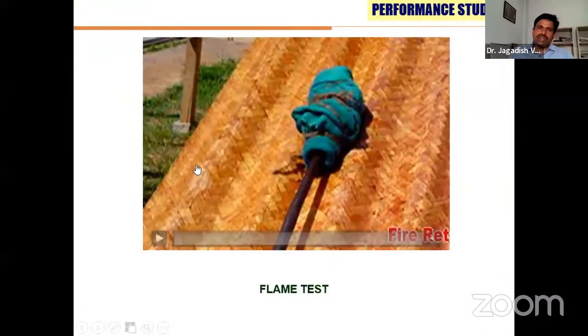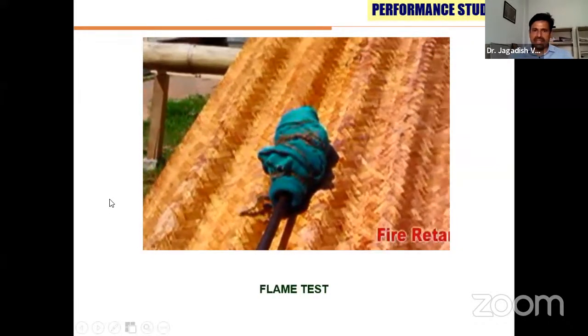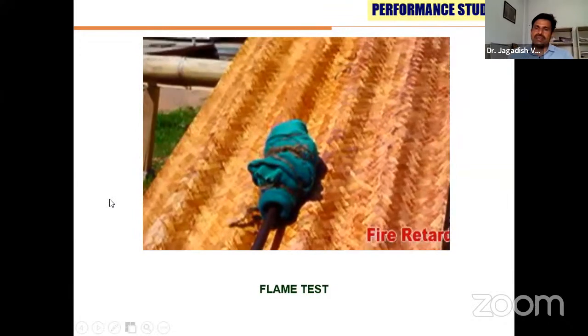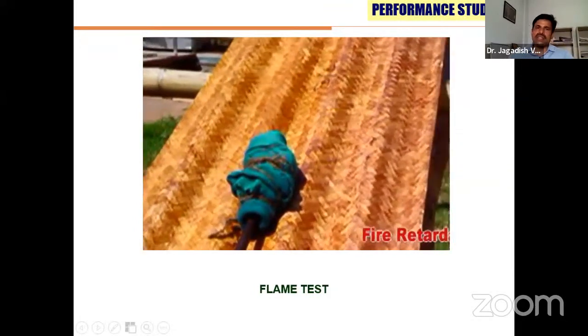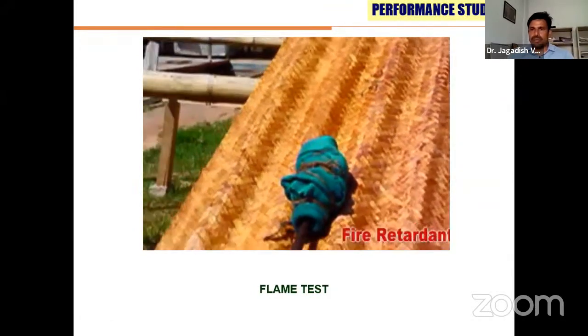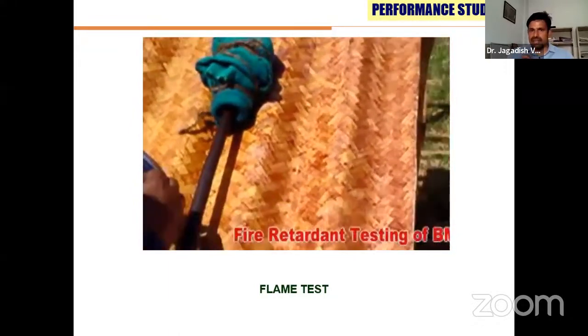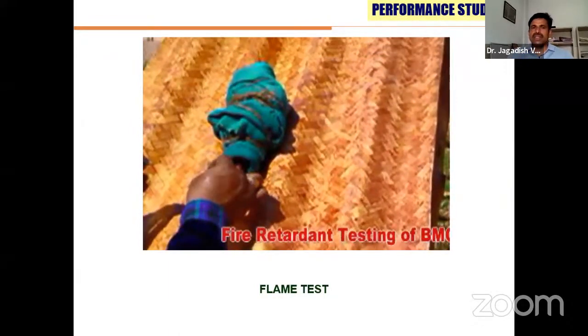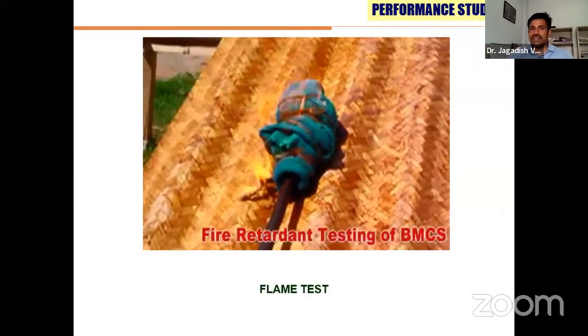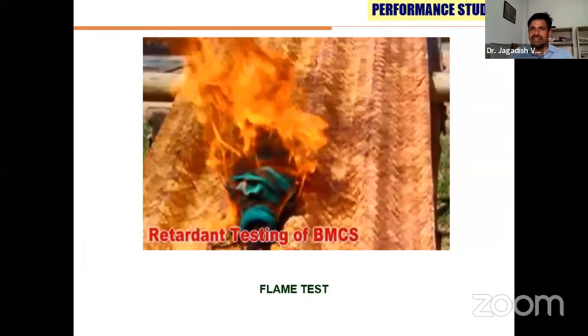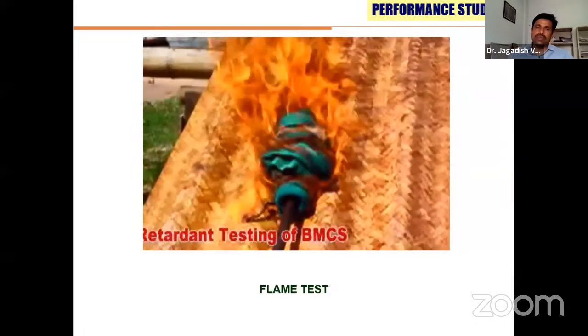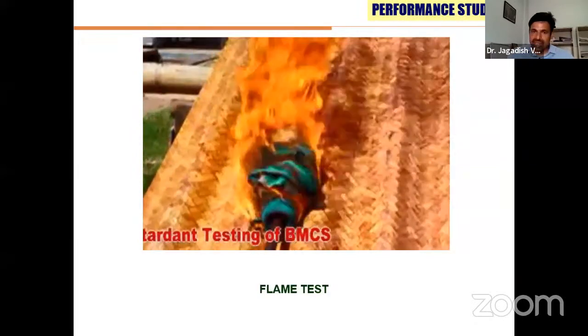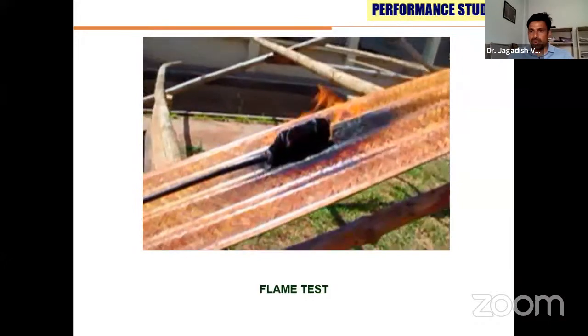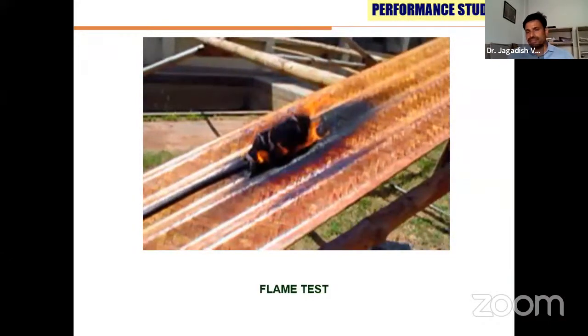Fire is one of the major concerns for the elements, particularly the roofing portion of the bamboo. Suppose you're using a bamboo mat corrugated roofing sheet, if you put it on fire, it won't catch the fire, but it will blacken the surface. This is what we observed. So one very important thing is the exposed fibers should be properly treated.